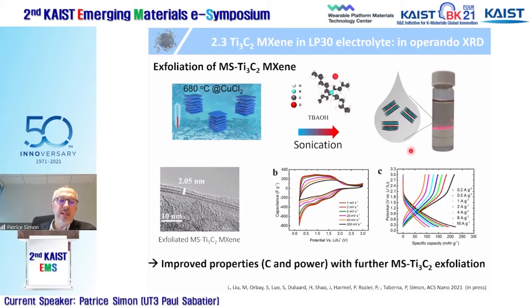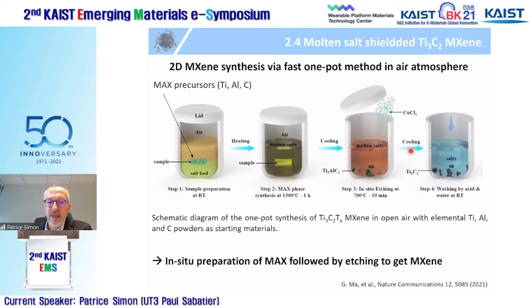And yes, finally, you can improve further the electrochemical properties in terms of capacity and energy with further exfoliation of your material. But a lot of work still needs to be done to be able to fully exfoliate, delaminate this molten salt prepared MXene. And then there is also, in a last couple of slides, another method which we recently published. It's a 2D MXene synthesis, but via a one pot method.